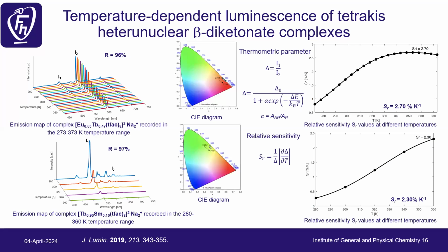And the second example is terbium samarium. Here we were looking also at the 545 peak in green of terbium and 650 of samarium. In this case, this was at the time one of the first in the physiological temperature range with samarium that we showed that it can be used. But this was a good opportunity for us to see what we can do further.